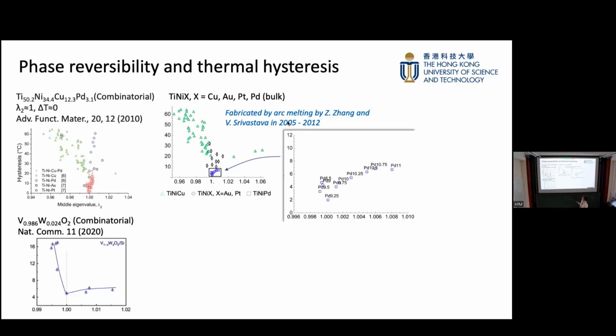And here is something very interesting. This is an oxide, not an alloy. This material was also fabricated by a similar combinatorial method, also thin film. And people also find in this material a tetragonal to monoclinic transformation, and the thermal hysteresis is also minimized at lambda 2 equal to 1. And here we have some unpublished results, which I don't think can be published because they were made by a previous postdoc and a PhD student long ago in the University of Minnesota's lab. After graduation, we still didn't publish this data, but I think it is very interesting.